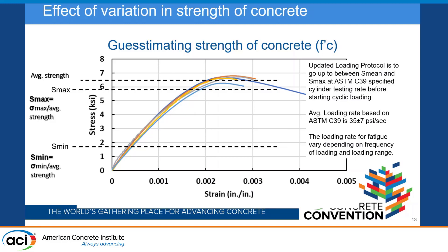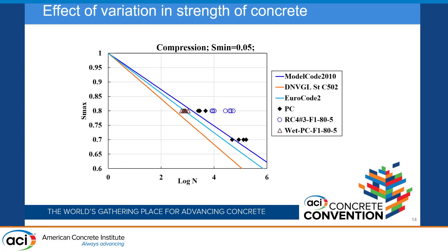The loading rate for cyclic loading is very high — about 200 to 1,000 PSI per second. For static loading, ASTM C39 specifies 35 PSI per second. So we load up to S-max based on the average strength at the standard rate, take the stress-strain response, plot it with our previous monotonic test, and guesstimate the strength based on that. The results had a very low range and were very impressive compared to the database we have.